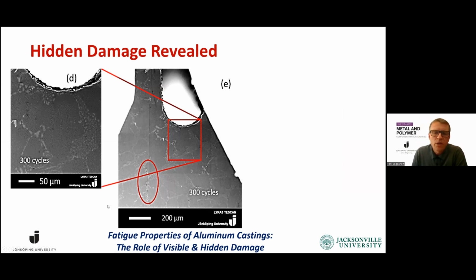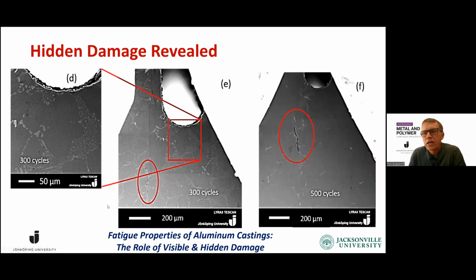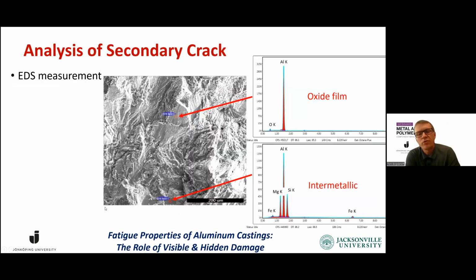So if we continue to the next picture, we actually see after 500 cycles that we have a lot of things opening up in the microstructure. However, nothing in the notch region where the strain concentration should be highest. So after failure of this sample, we investigated a fracture surface with EDS measurement and find different locations.